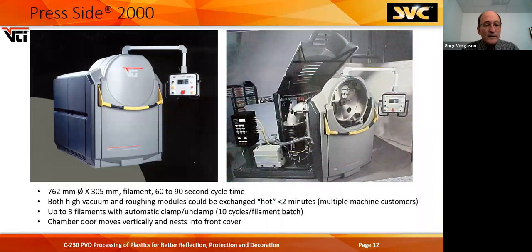And we got a little cooler. Still a 760-ish millimeter diameter chamber, but a little thinner. And we went to a flat fixture. Again, we started with filaments. Over on the right, you can see we had three filaments that came through. These were automatically clamped and unclamped filaments. At the end of 10 cycles, the operator could lift three filaments off very quickly and easily and drop three in.